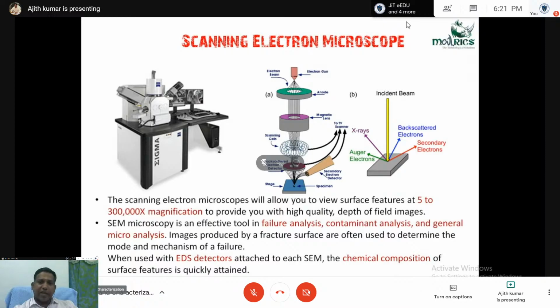From the scanning electron microscope, we can see a wide range of magnification, providing high quality depth of field images. Scanning electron micrography is an effective tool in failure analysis, contaminant analysis, and general microanalysis. Failure analysis means after fracture, after fatigue fracture, we can analyze the fractured surface using SEM. What kind of fracture, is it a brittle fracture or ductile fracture, we can understand from the scanning electron microscope.